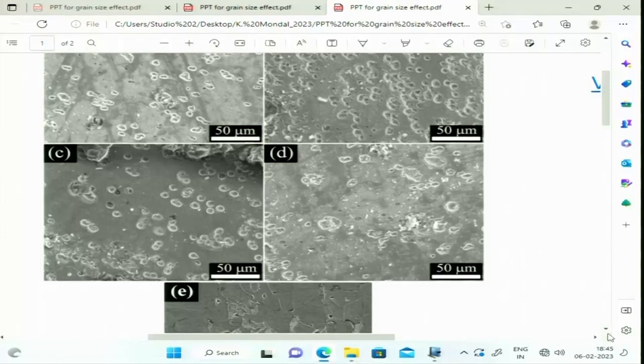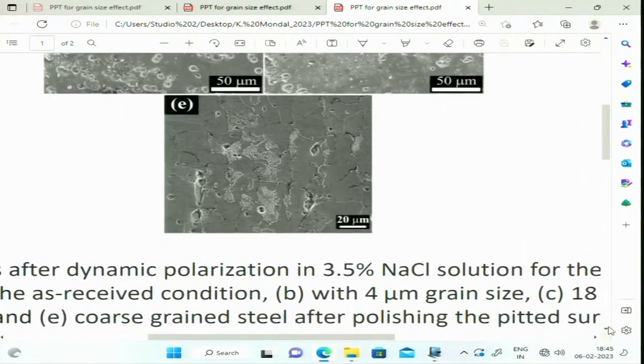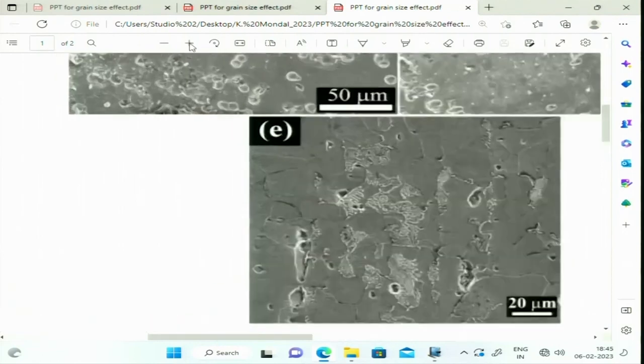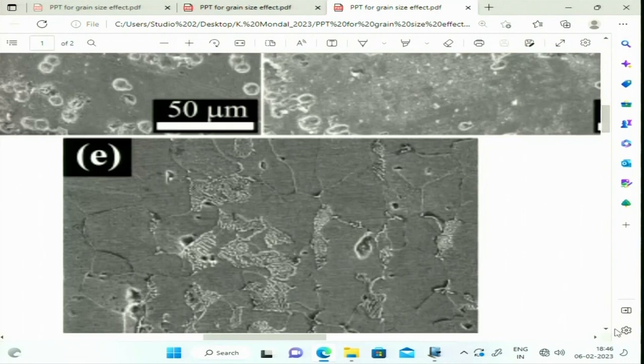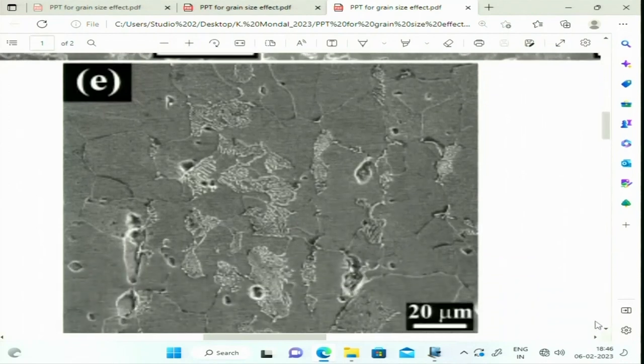Now, we have to see whether the attack is actually happening at the grain boundary. So, for that, we have taken a coarse grain material, which has a grain size of around 34 to 35 micrometer. This is the surface we are talking about now. Now, we could see some of the pearlites. If you see this cursor, these are the pearlite. And of course, you will find pearlite in case of 0.1% carbon steel, which is definitely mild steel. And there, as per the phase diagram, the steel part of the iron carbon diagram, we can calculate what could be the amount of pearlite there.